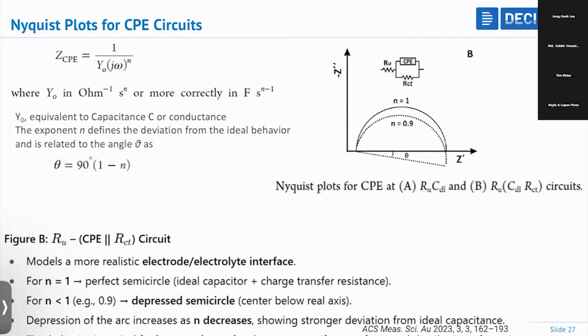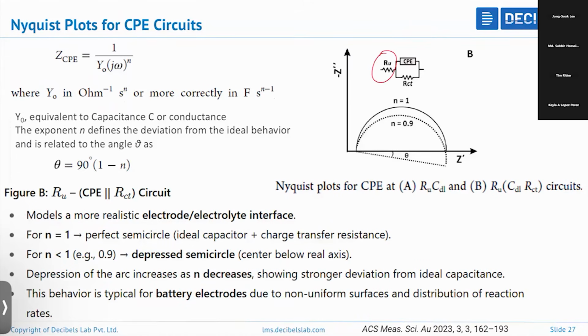If R is in series with this parallel circuit, then we get a Nyquist plot like this. This is corresponding to R, and the semicircle corresponding to this. You can see that we are not getting the perfect semicircle. There is a depressed semicircle, depressed by an angle theta. That value is about 0.1, about 10% depressed. This is because of 10% deviation from ideal behavior of the capacitor.